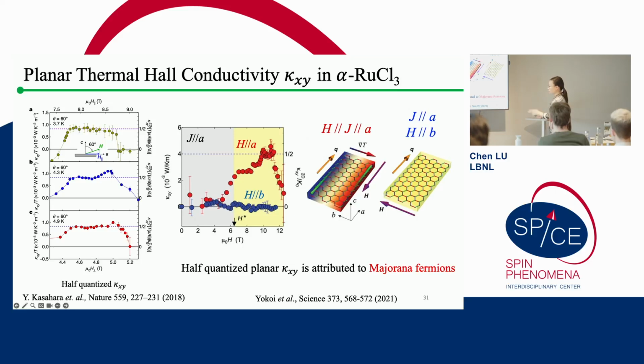But later on, they found this half-quantized thermal Hall plateau, which is the red curve in the figure in the middle. This half-quantized plateau even exists when you put both the field and the current in parallel to each other along the so-called zigzag direction of the honeycomb lattice. So this half-quantized planar thermal Hall plateau was believed to be generated by Majorana fermions.